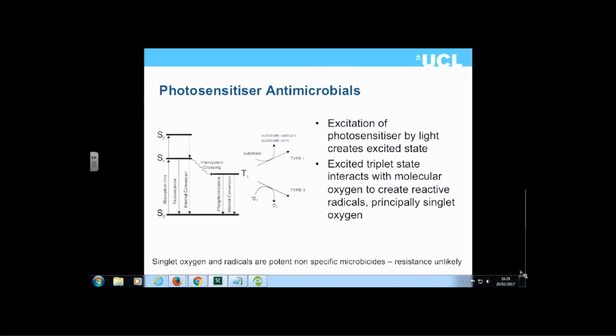What we've tried to do is develop coatings that will kill microbes or stop them from forming a biofilm. The way we've done that is using photosensitizers—using light to create an excited state of a dye incorporated into the surface. This antimicrobial surface will kill bacteria when you shine light on it, killing bacteria on contact.